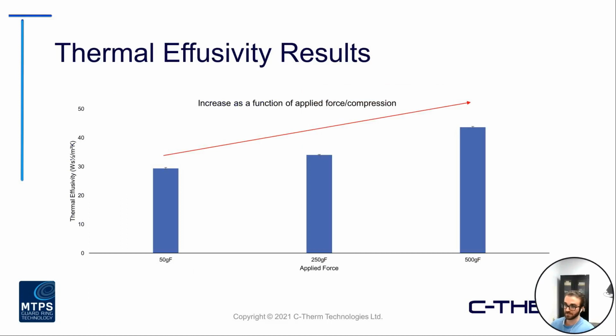And what we're seeing here, taking a look at the effusivity results, is essentially what we were expecting. The increase in effusivity as a function of the applied force or the compression, ranging from 50 gram force resulting in the lowest value, with 500 gram force being the highest. Now, I have this straight line showing that net increase.